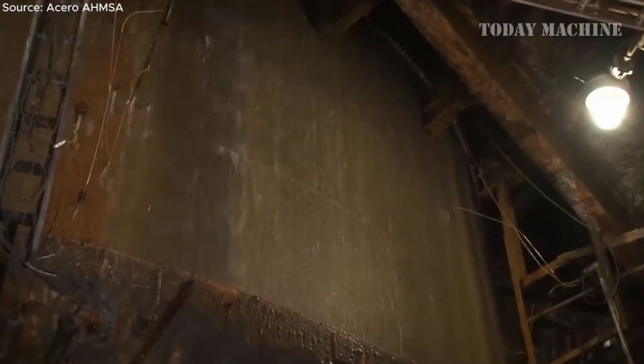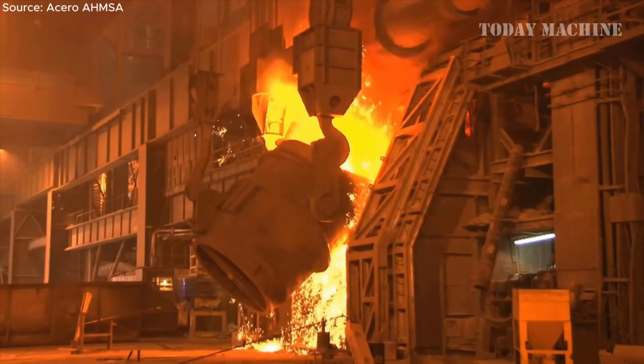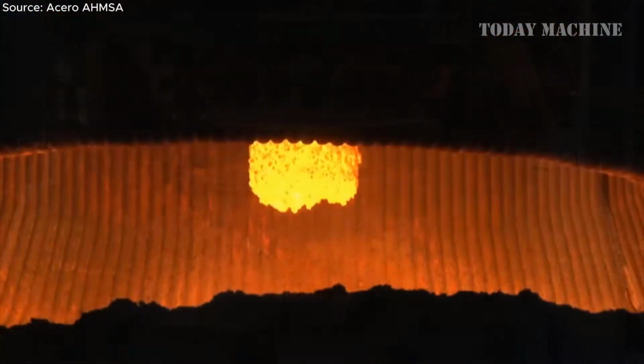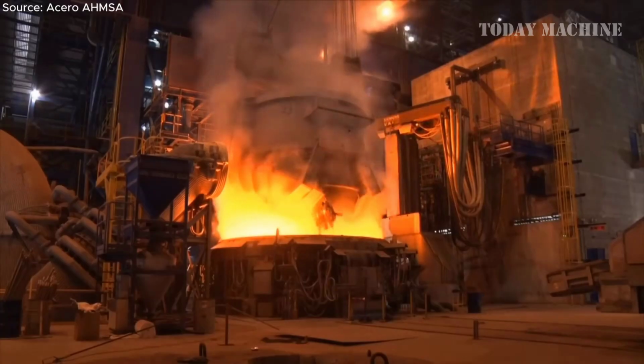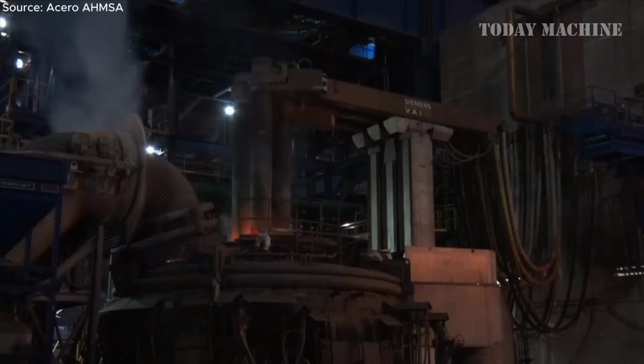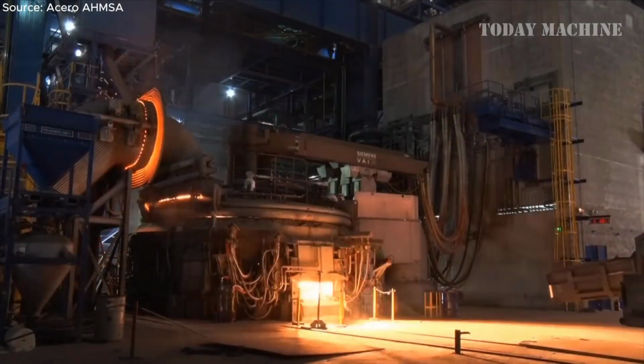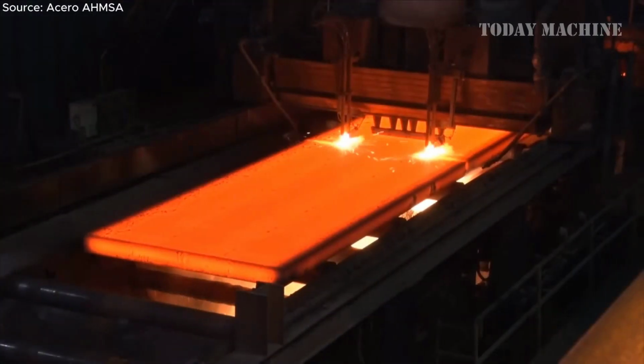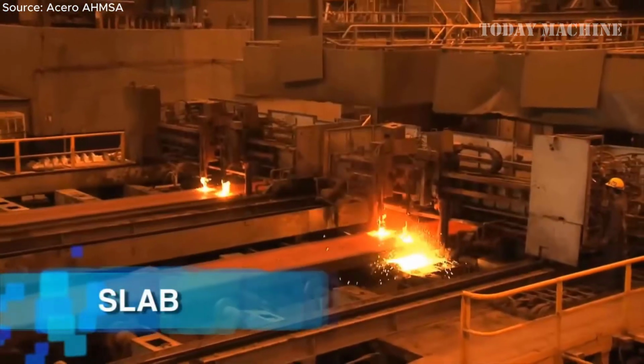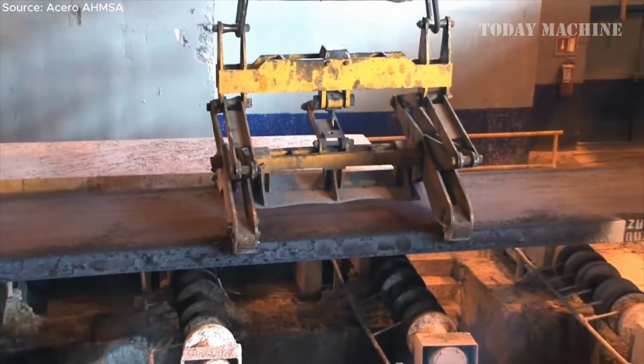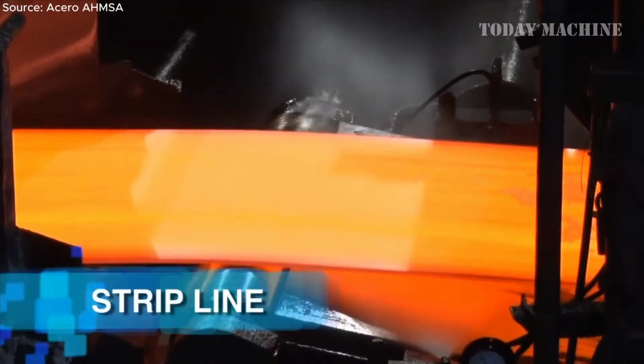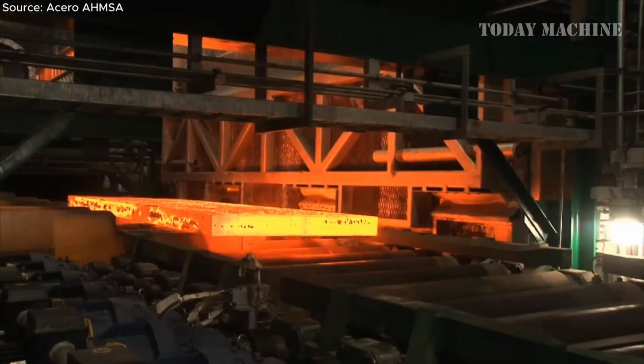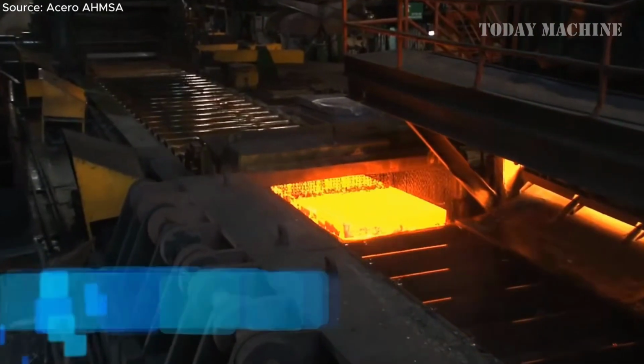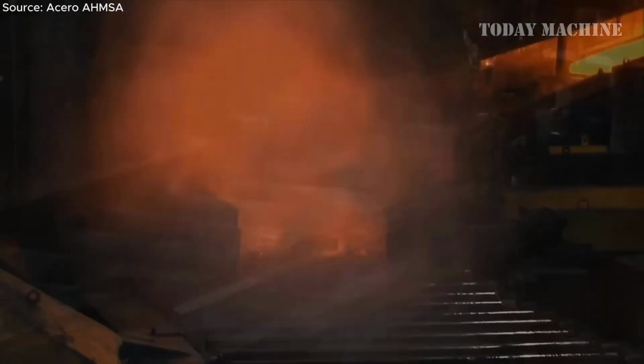Steel production at Altos Hornos de México follows a fully integrated process, starting from raw materials and ending with finished steel products. Iron ore from the mines undergoes pelletization, where it is filtered, mixed with binding agents, and hardened at 1,300 degrees Celsius. Meanwhile, metallurgical coal is transformed into coke through an 18-hour baking process, providing the essential fuel for blast furnaces. In these towering furnaces, raw materials, iron ore, limestone, dolomite, and coke are layered and subjected to temperatures of 1,650 degrees Celsius, reducing iron oxides into molten pig iron.